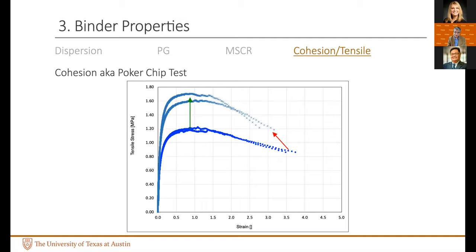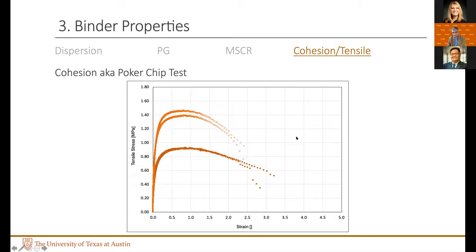What we did not do in mixtures that we did with asphalt binders was also to add the elastomer. And you can see the elastomer now helps bring back some of that ductility with this particular binder. And you'll see it's the same trend with the next binder. Again, the bottom line is control. The top one is with the plastic, increase in tensile strength, decrease in ductility, and you add the terpolymer, it brings it back.